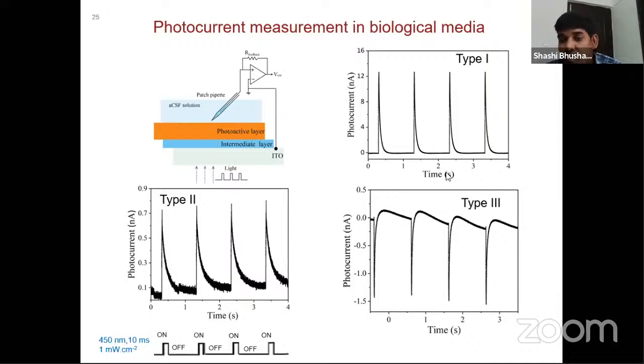So we found the capacitive mechanism, and when we calculated the area of these two parts, the on and off time, we found that it is almost equal, which shows that it is a pure capacitive behavior of the device. And I forgot to tell you that when we shine the light, we see this kind of behavior, and this light is a pulse light, which is on and off. It is the blue light, 450 nanometer, 10 millisecond, and 1 milliwatt per centimeter square. It is very low intensity if you compare the solar cell operation at 100 milliwatt per centimeter square. So 100 times lesser intensity than the solar intensity.